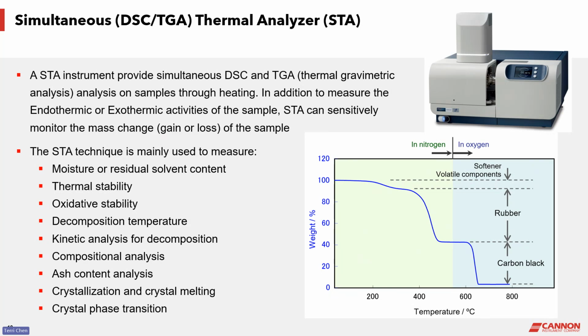For example, it can measure moisture or residual solvent content, monitor sample decomposition, calculate decomposition kinetics, and measure thermal and oxidative stability. It is also commonly used for compositional analysis of filled polymer composites. The STA is also a good high-temperature DSC, which can measure crystallization, crystal melting, and crystal phase transition.